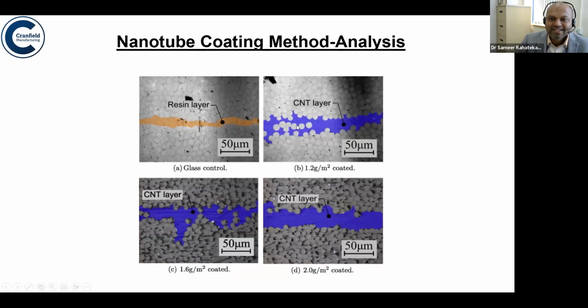And what we found from our research is that if you use just a composite without carbon nanotube modification, you have between two layers. This is one layer of composite, and this is a second layer of composite. When you join them, there is a region where there are no fibers, okay, only glue. Okay, so that's this region, resin rich layer, and that is easy to fail. Or when I say easy, it's less strong than this region. But if you add carbon nanotubes in this region, that is shown by this, the colors are not true colors, they're just highlighted to get you a better visualization. But now with carbon nanotubes between this joining layer, this layer becomes stronger, and therefore you can get better mechanical properties by adding carbon nanotubes between two layers of composite. And you can really increase the fracture toughness.